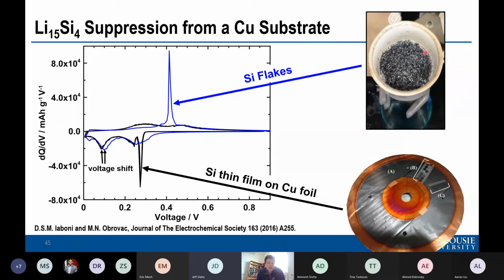So in this powder that he made by grinding up this stuff and putting it in a composite coating, you got a lot of cracks and all these uneven surfaces and points and fissures that the lithiation can start in. The lithiation has to nucleate somewhere. It has to get into the material somewhere. On a perfect, nice, smooth, sputtered film, it's very hard for the lithium to nucleate. There's not very many nucleation sites. So you can see this initial lithiation starts here in the composite coating, but it's pushed to lower voltage. And then you get rapid nucleation because it's basically under potential lithiation now. And so this is from nucleation and growth in a thin film.